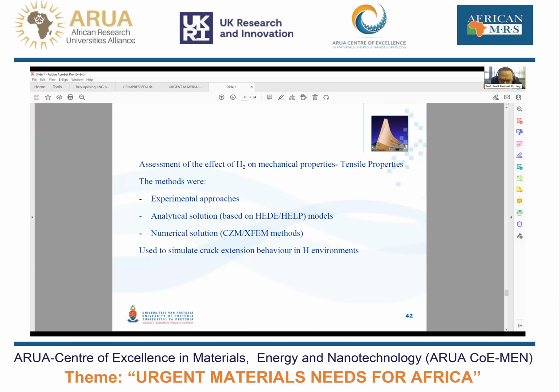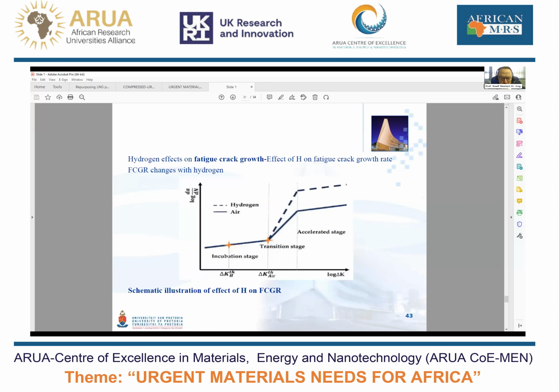So in the literature, there are a number of ways to check the impact of the hydrogen on the mechanical properties. Some of them are also numerical methods. Experimental methods are obviously still the gold standard. So this slide demonstrates what happens in a fatigue environment with pressurized hydrogen. This is a fatigue crack growth rate curve, and it's been shown by many researchers that the hydrogen results in accelerated fatigue crack growth.